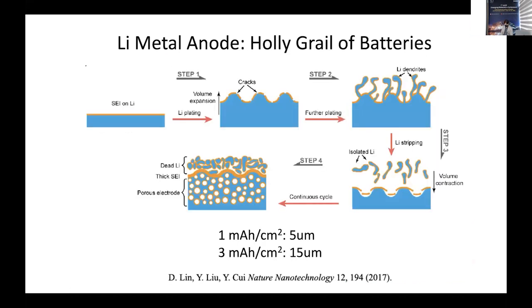So with this silicon design, the holy grail of the battery is really the metallic lithium anode. Metallic lithium anode has no host. It's just lithium metal by itself. So during charging, it will go through this electrodeposition process. During discharge, there will be electrochemical stripping. So during this process, the thickness change of the electrode is very dramatic. In this perspective article we published in Nature Nanotechnology, we point out to the community that this volume change is too dramatic. There is no host. The relative volume change is infinite.